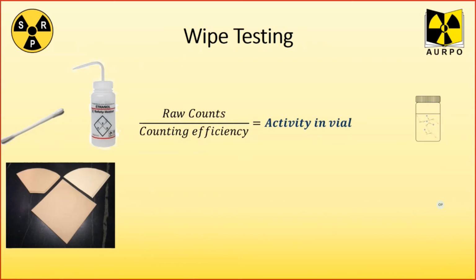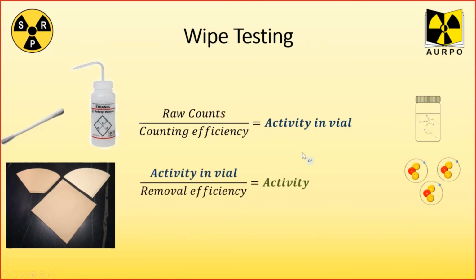So how do you get from the counts that come out of the machine to a value that you can report against? You have your swabs, and you'll get a value. You need to divide it by the counting efficiency. You will need to determine that yourself, or use a value that you think is conservative. We could use a value of say 50%, which is fairly low. That'll give you the activity that's in the vial from your swab. However, you then need to consider how much has actually been removed and what's left on the surface. So you take the activity from the vial and divide it by the removal efficiency that you've determined, which could be 10%.